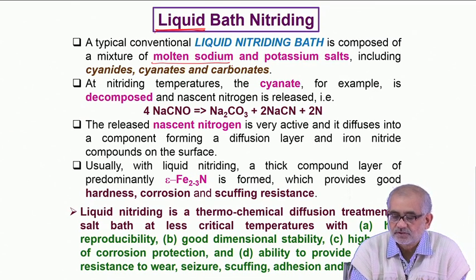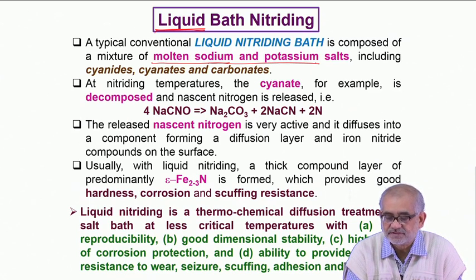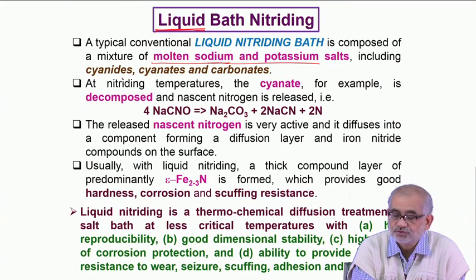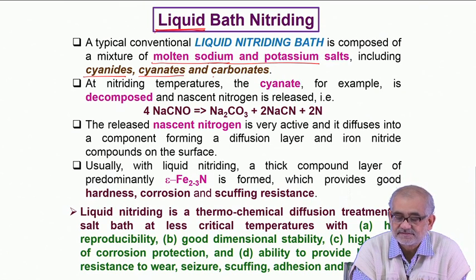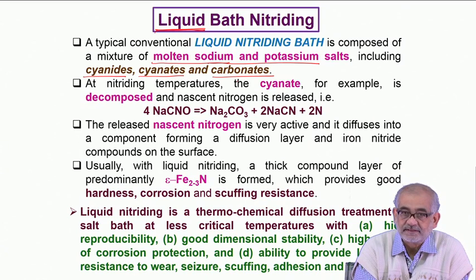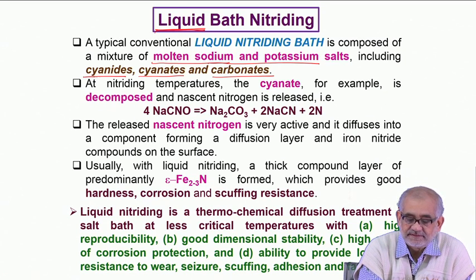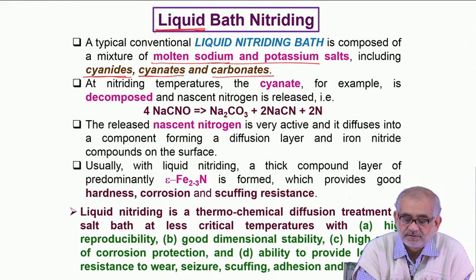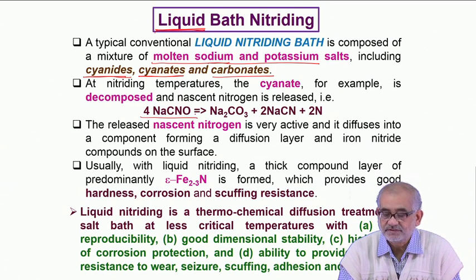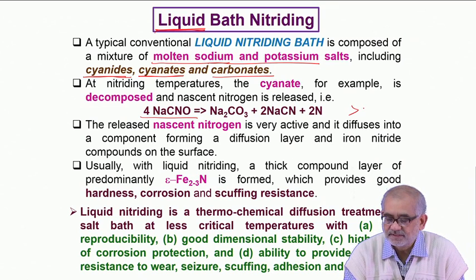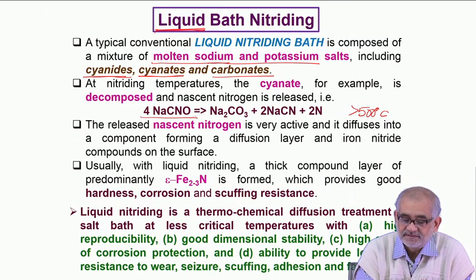So, as I said, we deal with molten sodium and potassium salts, and they are usually cyanides, in some cases cyanates and carbonates. Carbonate is more like an activator, but cyanide is the main source of nitrogen. In many cases we do not deal with cyanide directly because it is extremely toxic. We deal with cyanates. For example, sodium cyanate, at the temperature where we do the nitriding process, typically about 500 degrees centigrade, decomposes into sodium carbonate and, most importantly,